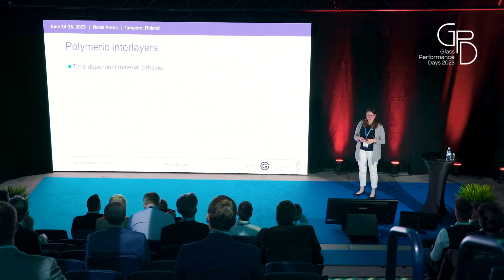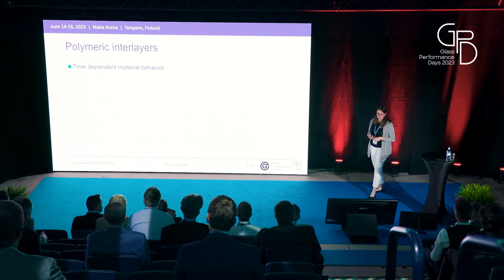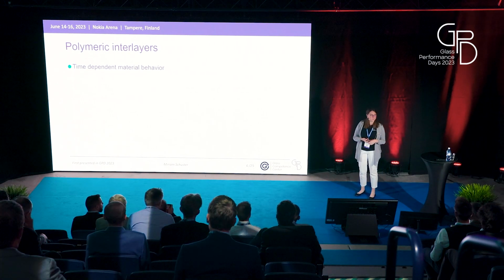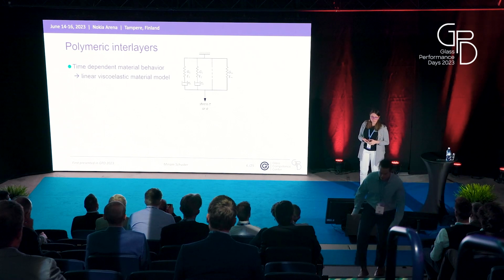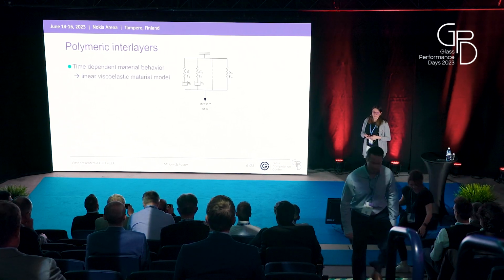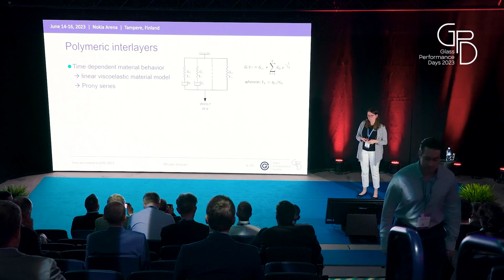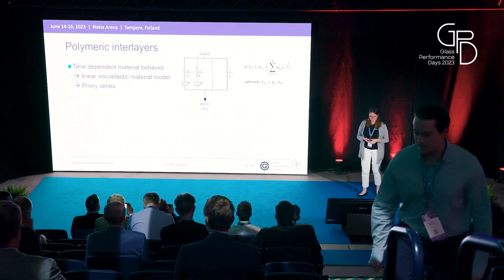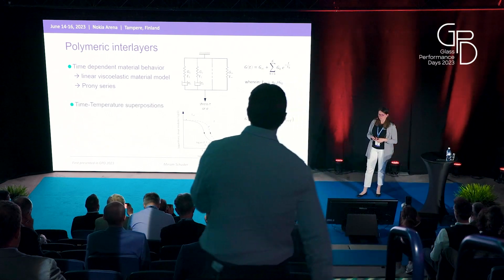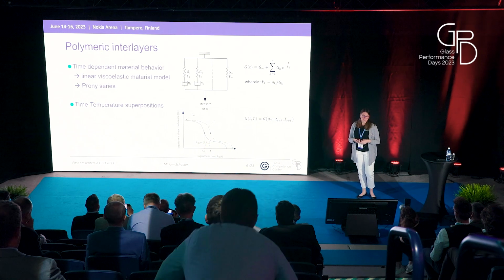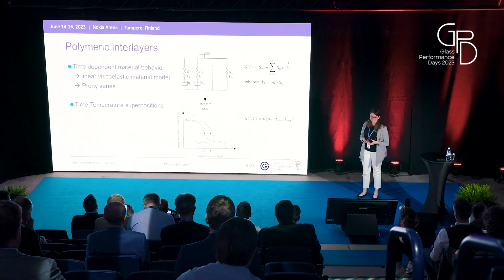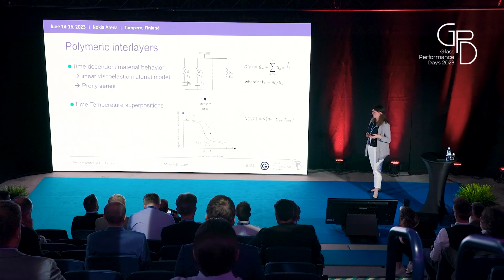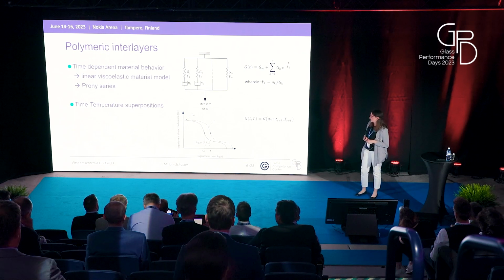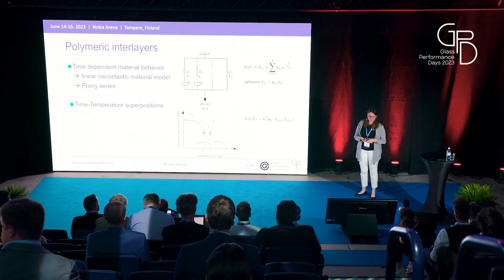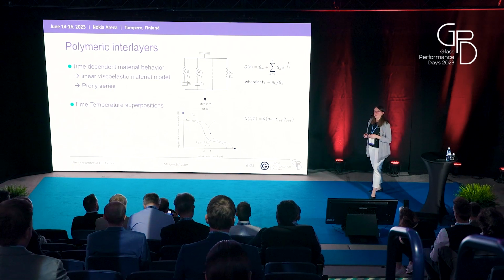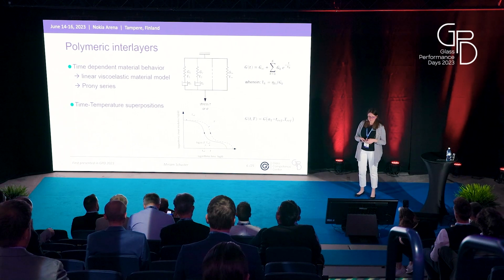But first, let's have a look at the material behavior of polymers in general. As we all know, there is a time-dependent material behavior which can be described in the linear viscoelastic way by a generalized Maxwell model and mathematically be described by a Prony series. Thermorheologically simple materials also have the advantage that the temperature dependency which occurs in all the polymeric interlayers can be described with a shift factor, which means that when we change the temperature, the relaxation function is shifted along the time axis.